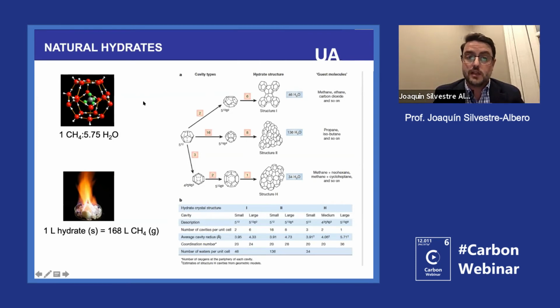And as I say, this is the natural way that you have on Earth to store methane. And this is very interesting because 1 liter of hydrate is able to store 168 liters of methane. So this is a very interesting way to store large quantities of methane. These hydrates are not only restricted to methane, so you can put in the cavities other small molecules like CO2, helium, hydrocarbons, and in fact, depending on the molecule that you're introducing in these cavities, there is a different structure for the system. No?